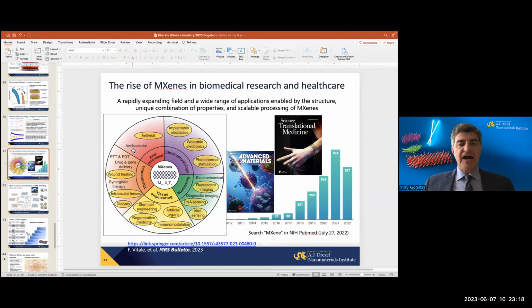Is this a release of ions adsorbed between the layers of MXenes? Is this like cutting bacterial membranes by the edges of MXene flakes, or anything else? However, combining it with very good biological compatibility, blood compatibility, and low cytotoxicity, it should definitely, in my opinion, be not a mechanical mechanism, but a chemical one. But which one, I don't think the community agrees on this yet.